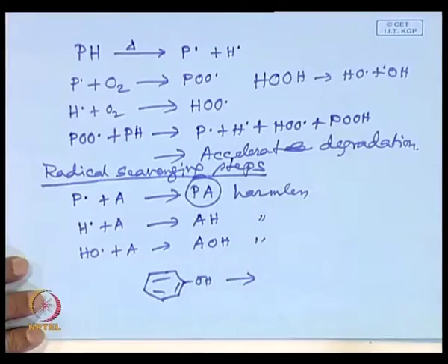That stable radical will scavenge those degrading free radicals. So, you see phenol formaldehyde products, phenol formaldehyde composites are stable, they do not degrade. Oxidative degradation of phenolic composites is almost nil, minimum. So, woods which contain lignin are stable, because lignin contains phenolic units.